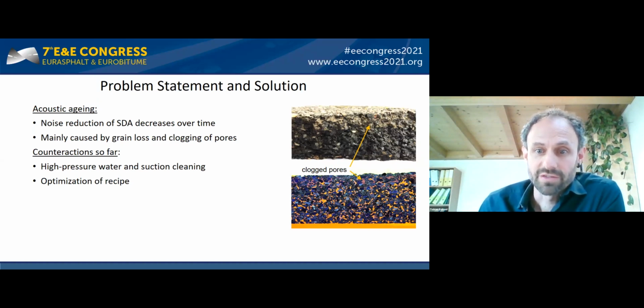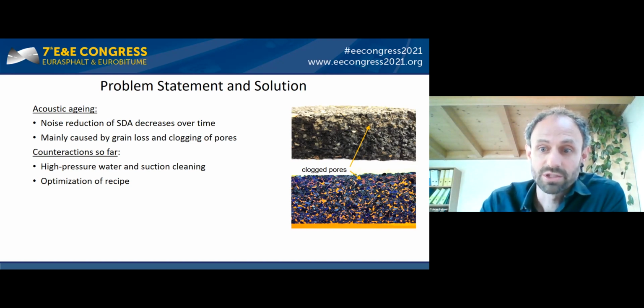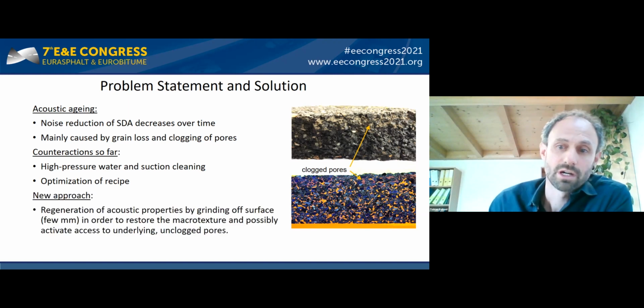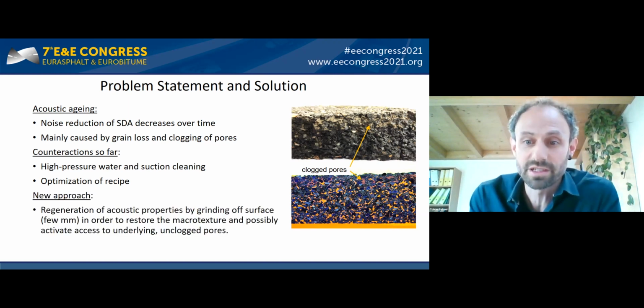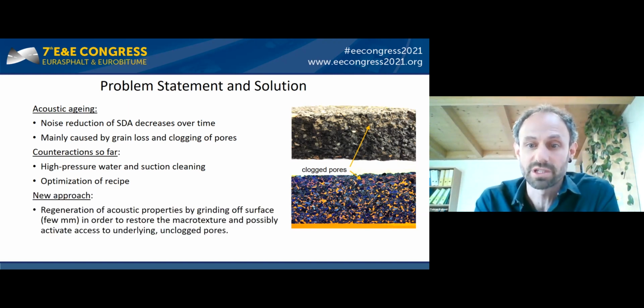In the later part of lifetime, oxidation, weathering of the bitumen sets in, and also grain loss occurs, which attributes to additional vibrational noise. Optimization of the recipe so far only helped to improve acoustics after laying, but not to prevent grain loss or cracking over long term.